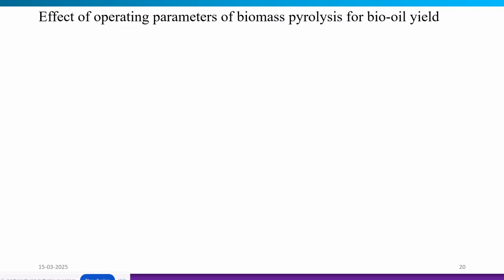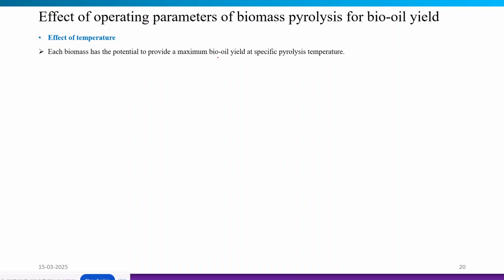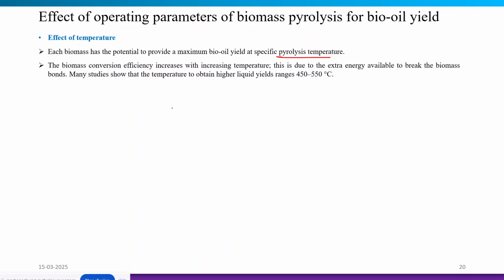We will now discuss some of the important operating parameters that affect the biomass pyrolysis process for bio oil yield. First one is temperature. Each biomass has the potential to provide maximum bio oil yield at a specific pyrolysis temperature. The conversion efficiency increases with temperature due to the extra energy available to break down the biomass molecular bonding. Studies reported that higher liquid yield is obtained in the range of 450 to 550 degrees Celsius.